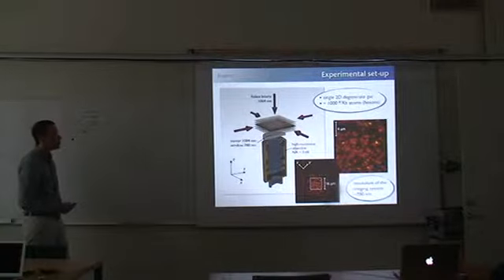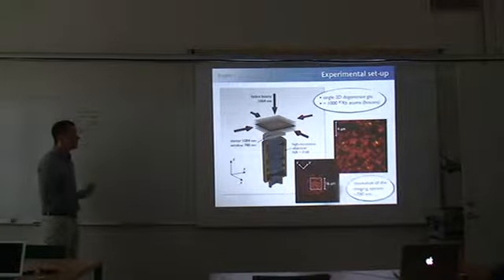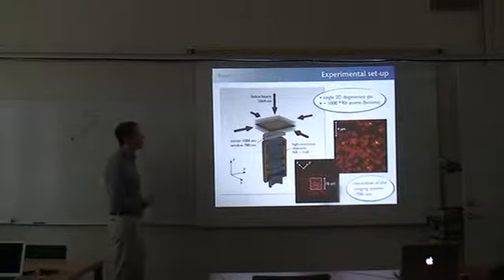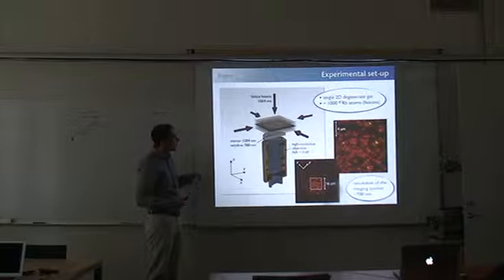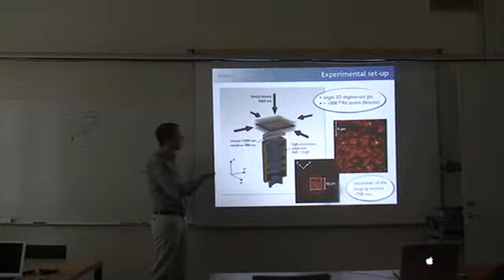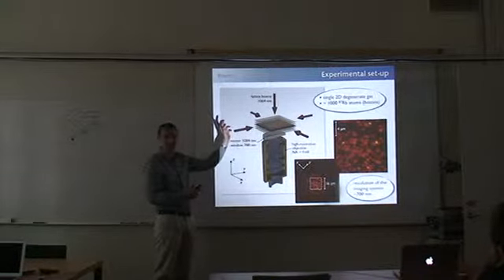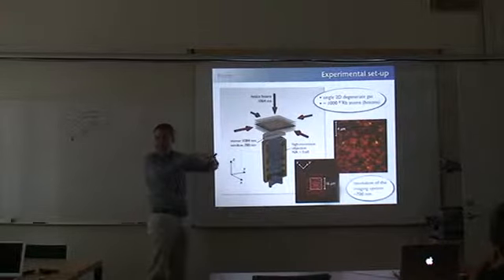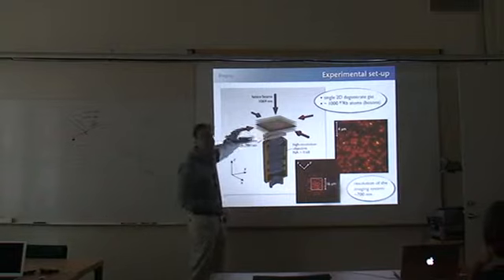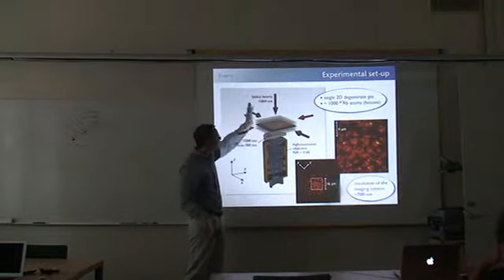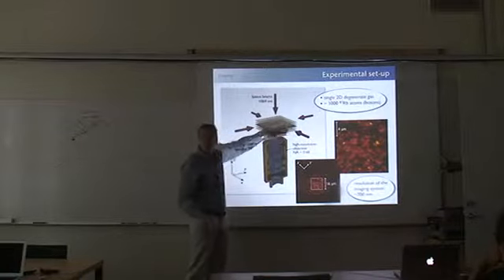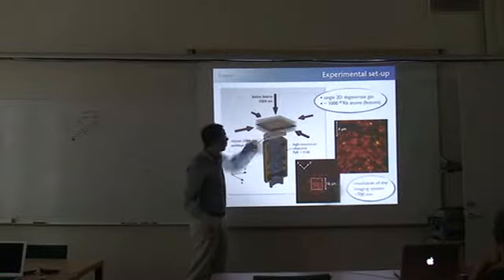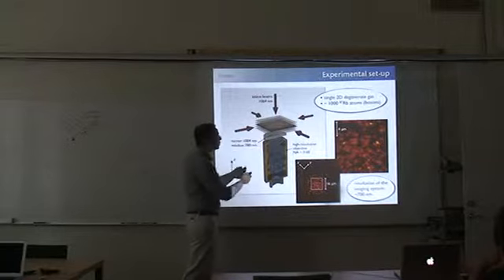So let me tell you about our system. Our experimental setup to do this is different from Marco's setup, but the conceptual ideas are, I think, the same. What we're doing is basically creating, first of all, a three-dimensional crystal of light by having, again, these 3D standing waves. One standing wave here, one standing wave here, one standing wave which is reflected off a mirror down here, which serves also as a window through which we can observe the quantum gases at another wavelength. Okay? So basically you get these two-dimensional planes. We have 2D lattices, and from these 2D planes we pick out a single one. By magnetic resonance addressing, we can apply a magnetic gradient field and take out a single two-dimensional plane from this crystal.